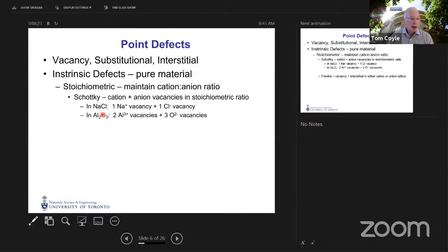In sodium chloride, a Schottky defect would consist of one sodium vacancy and one chlorine vacancy. In a little more complicated structure like aluminum oxide, a Schottky defect would consist of two aluminum vacancies, because there are two aluminum in the formula unit, and three oxygen vacancies, again, because there are three oxygen in the formula unit.